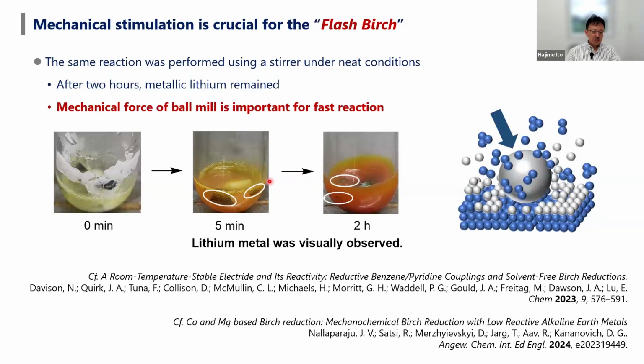This means that, of course, our reaction can finish in only 1 minute. This shows that mechanical agitation on the surface of lithium in the presence of substrate is very important for these high-speed reactions.